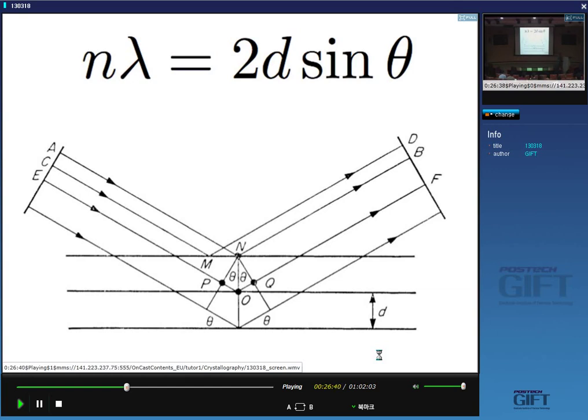Now, supposing that we deviate from the Bragg angle theta where this equation is satisfied, okay? So the Bragg angle is the angle where this equation is satisfied. Supposing we deviate by a small amount from the angle theta, then as I go deeper and deeper into the crystal, I will eventually be able to find a wave which is exactly half a wavelength out of phase, and you'll get destructive interference. Okay. But if the Bragg law is satisfied, I never reach that condition. I will get diffracted intensity. So the important thing is that the Bragg law applies for a crystal which is infinitely thick.